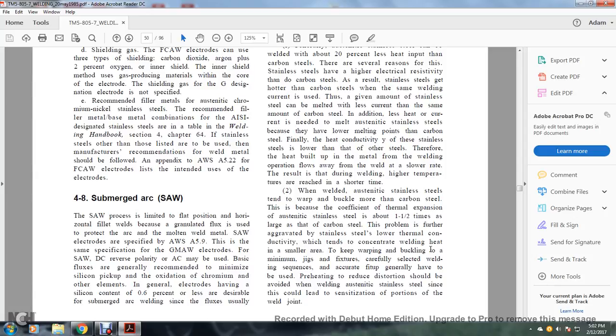To keep warping and buckling to a minimum, jigs and fixtures are carefully set up along with the welding sequence, and accurate fit-up of the joint has to be used. Preheating to reduce distortion should be avoided when welding austenitic stainless steel, since it could lead to sensitization of the welded joint.